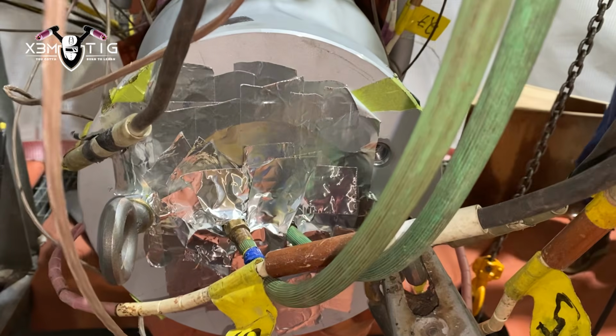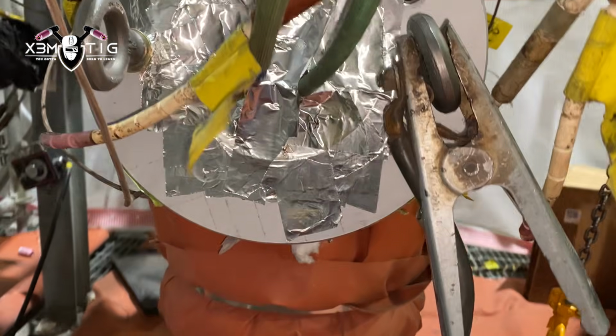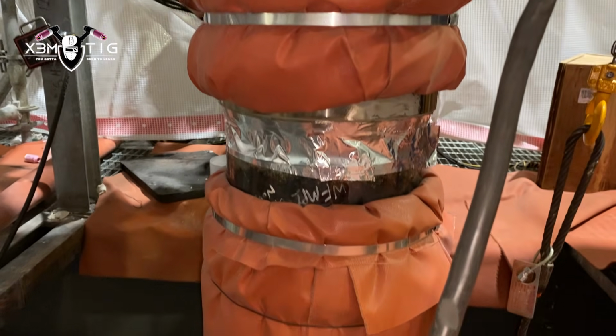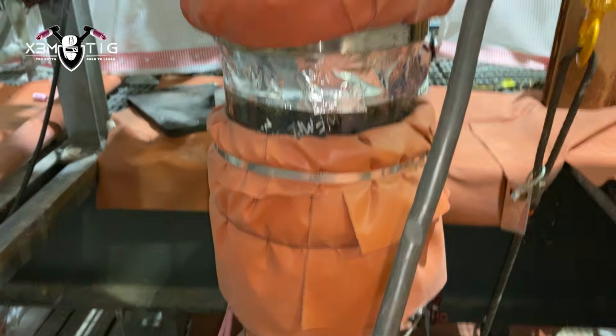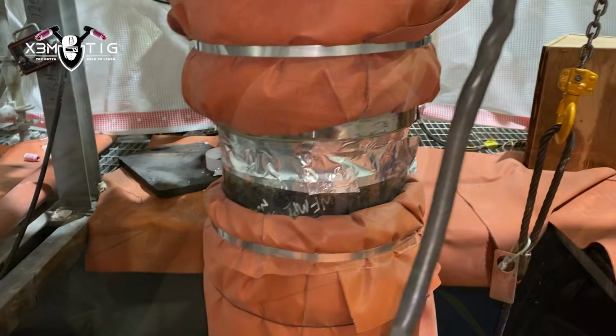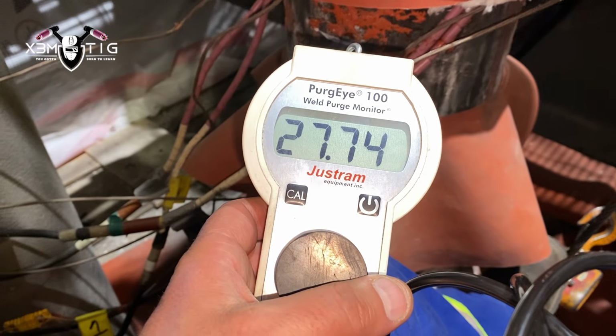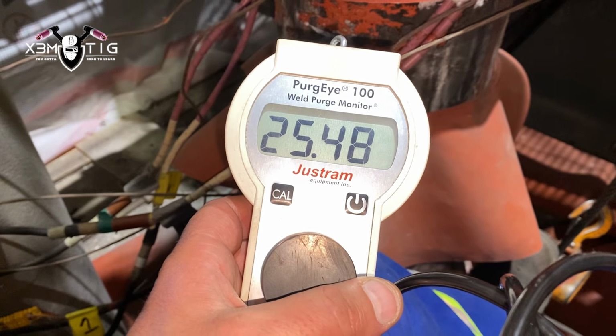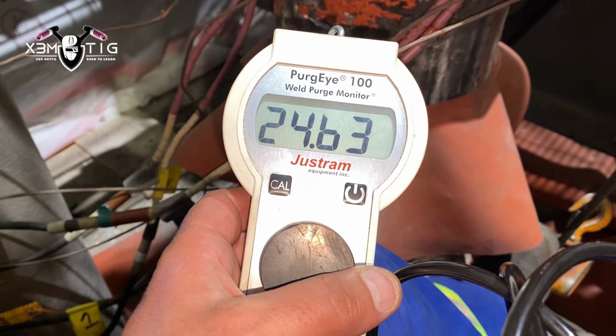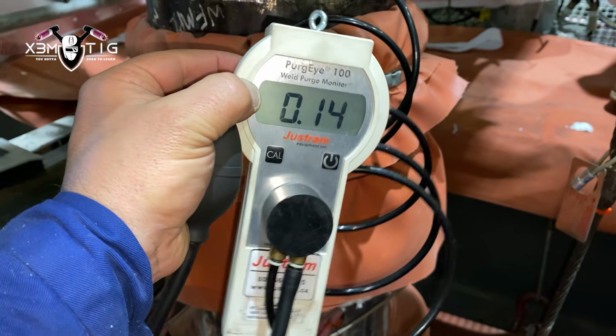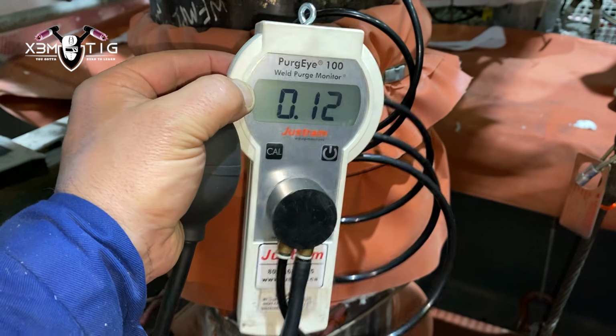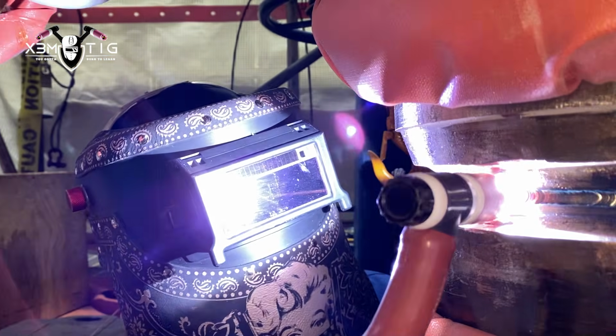Okay, two purge lines here as well. I'm going to check with a PurgEye 100 to make sure there's no more oxygen left inside. Once the oxygen levels drop below 0.5, you're pretty good to go.